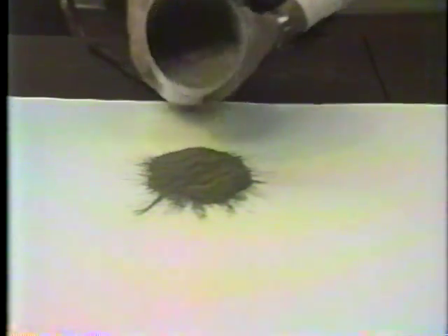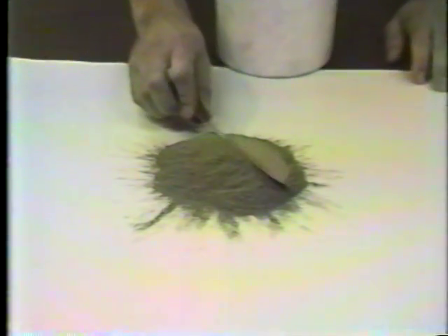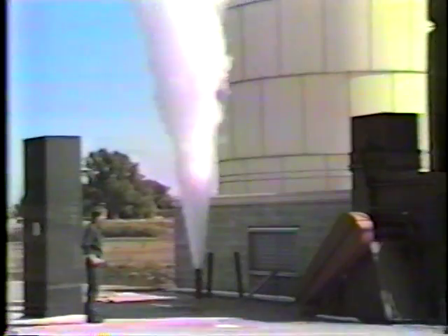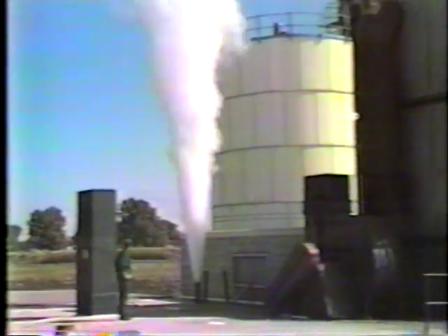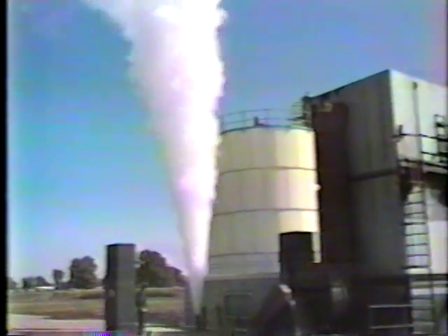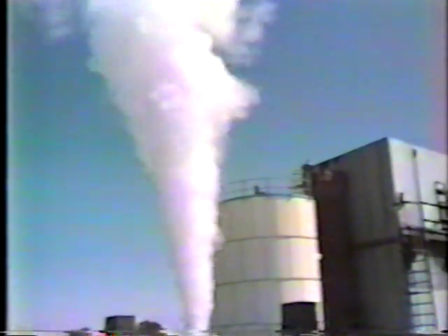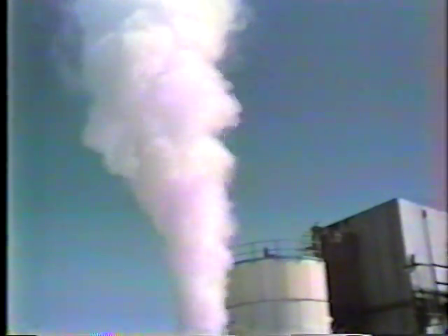And this is a sample of the baghouse ash as collected from the micropulse baghouse. It is 92% minus 37 micron and contains only 1.6% free carbon. When in normal operation, this steam will be used to process and dehydrate 1 million pounds of potatoes daily. The conversion from natural gas to coal is presently saving Idaho Supreme potatoes over $125,000 per month.